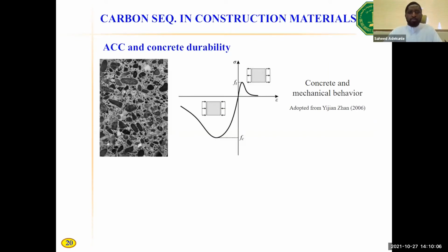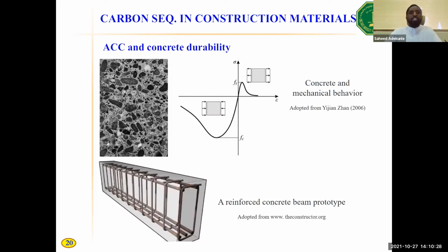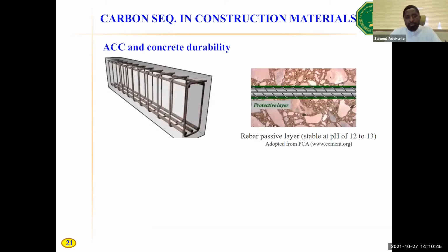Now, let's talk about the problems with the ACC technology, okay? It is important to note that concrete as a mechanical material is weak in tension and very strong in compression. And due to the weak tension response of concrete, it is traditional to place steel bars in concrete to enhance its mechanical response. Now, if you use a concrete member containing steel bars in ACC technology, the result is not favorable. Because as shown on the screen, there is a passive layer over the steel bar in concrete. This passive layer developed because concrete is a highly alkaline material. This high alkalinity between 12 and 13 pH makes the passive layer over the steel highly stable.